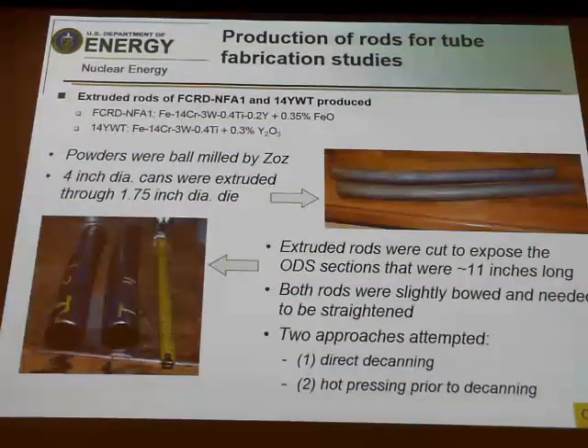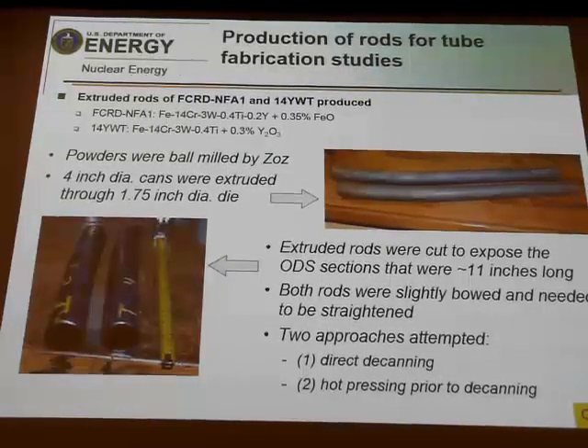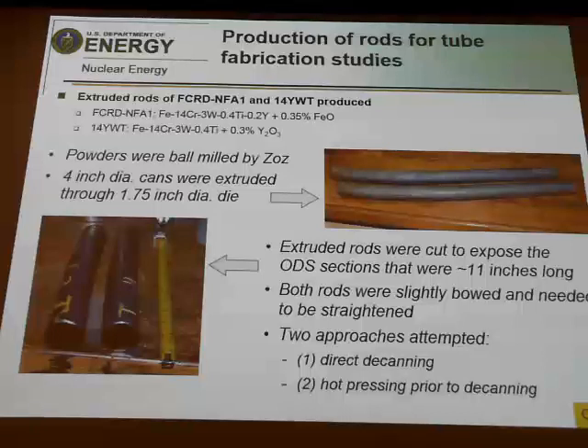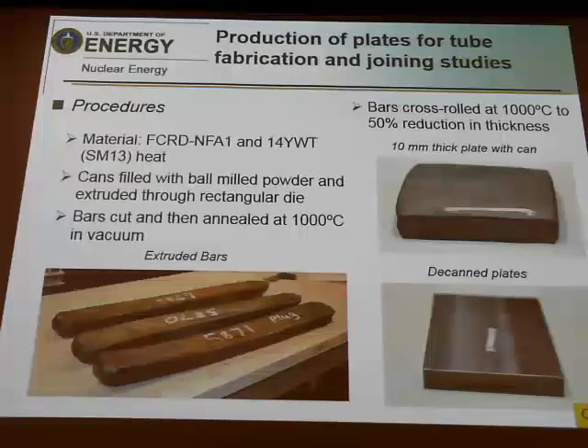Here's material that we've extruded now into long rods, which would then be further extruded into tube form. Like I said, these were initially ball milled by Zoz in 15 kilogram batches, and then we took the ball milled powders, put them into cans, evacuated the cans, and then extruded them at 850 degrees C. And in some cases, we had to even straighten them afterwards. Then we need to extrude that material further to make tube forms out of it, and that's one of the difficult processes.